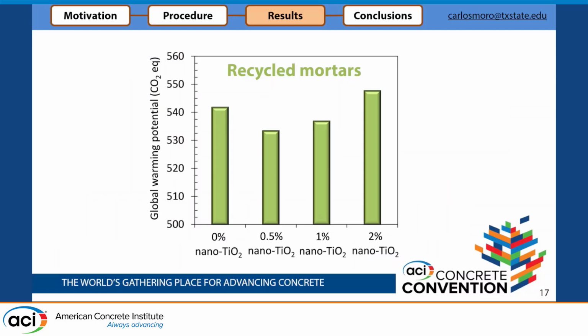If you focus only on global warming potential, so I show global warming potential or CO2 emissions on the y-axis, and then different types of nano titanium dioxide with recycled mortars. That means that this is 100% recycled concrete aggregate. We can see that a small percentage of nano titanium dioxide helps decrease because of the increase in compressive strength. So in that case, you can reduce cement content and you can reduce the emissions. But if we go further, that means that we use 2% of nano titanium dioxide, then it's not useful anymore, because basically you need more cement to achieve the same properties.